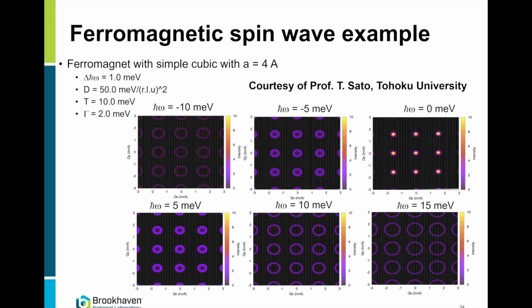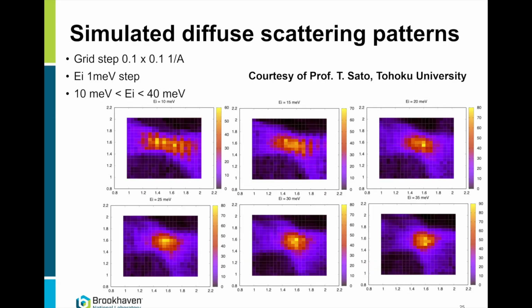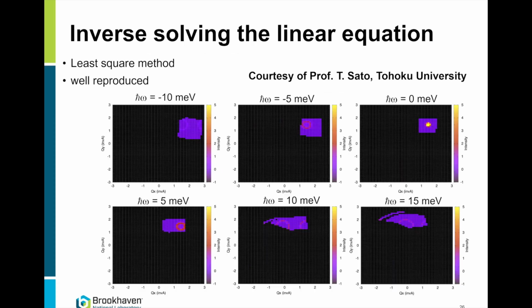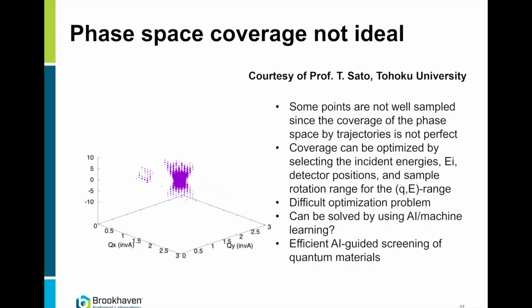So he made this calculation example of a ferromagnetic spin wave, which should look like that. And then if you do several steps in EI, you would obtain the diffuse intensity on your detector, which would look like that. And then you invert it back, and you obtain your spin wave. Of course, this inversion is imperfect because the coverage of your phase space is uneven. But the technique is extremely powerful. Now we can do neutron spectroscopy on tiny samples in a reasonable amount of time using a diffractometer at a reactor source.